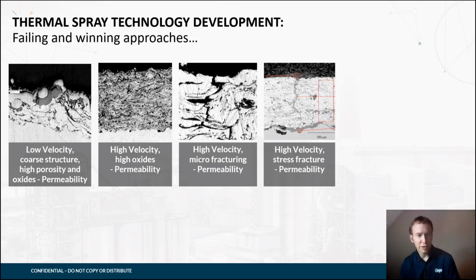If we have highly stressed materials, so when we apply thermal spray, we build up internal stress, then we can see cracking. So macro cracking straight to the substrate or micro cracking. In a corrosive environment, those cracks become pathways to the substrate that can then lead to failure of the system.